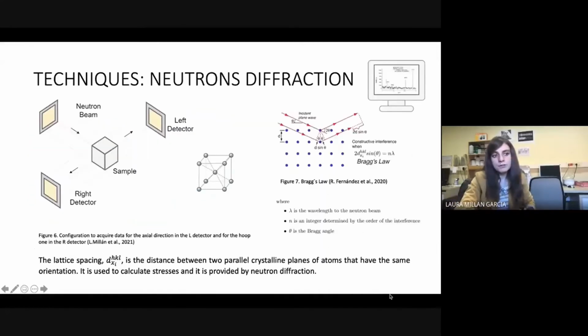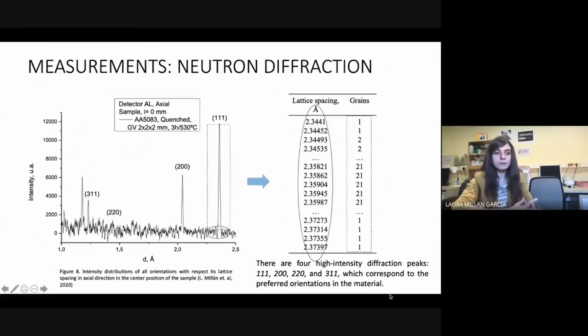We commonly measure the stress using neutron diffraction. The neutron beam passes across the sample and collides with the atoms of aluminium. The diffracted beam gives us the value of the lattice spacing between planes of atoms which have the same orientation. This parameter is important to calculate the stress. Besides, we can obtain a diffractogram with 4 peaks according to the principal orientation of the grains: 111, 200, 220, and 311.